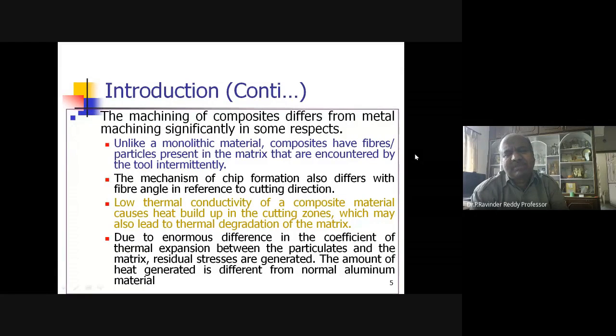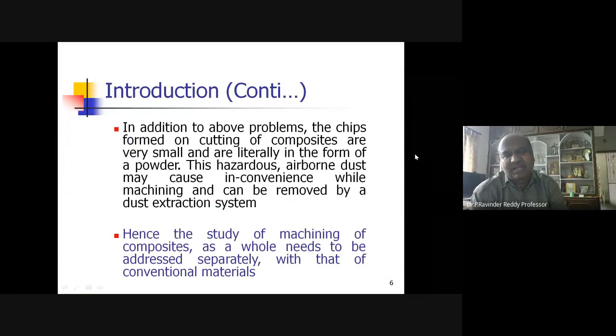Low thermal conductivity of a composite material causes heat buildup in the cutting zones, which may also lead to thermal degradation of the matrix. Due to the enormous difference in the coefficient of thermal expansion between the particulates and the matrix, residual stresses are generated. So here one observation you can make: because it's a composite, we have particulates with a different thermal conductivity, and the fiber and the matrix have different thermal conductivities. So here residual stresses differ from location to location. A local finite element model, whenever you go for simulations, is essential because we have to assign the properties accordingly. The amount of heat generated is different from a normal conventional material when you use it for numerical or experimental operation.